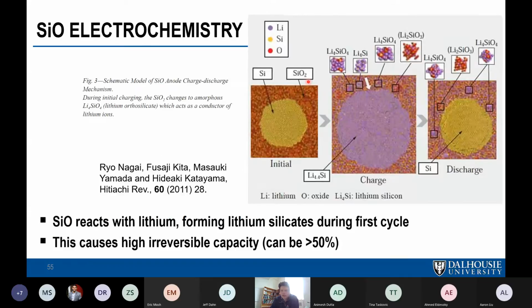I did say that I was going to say something interesting about SiO, which was, if you calculate the volume expansion or the volumetric capacity of SiO as a function of oxygen content, you will get a very interesting result. That might be an interesting exercise, or Jeff, I could just say what the interesting result is. Up to you. You can say what the interesting result is. I will say it. The volumetric capacity of Li4SiO4 is almost identical to silicon. The molar volume per lithium is 12 for both of them, for Li4SiO4 and lithium 15 silicon 4. So the volumetric capacity of SiO is identical to silicon for the first lithiation at any oxygen content. It's a straight line. It's pretty nice.